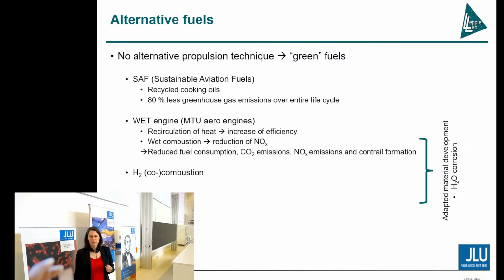Then there's also the so-called wet engine by MTU Aero Engine, where they recirculate the excessive heat and thereby increase the efficiency. And they introduce the condensed water from the end of the turbine in the combustion chamber and thereby have a wet combustion. And by this wet combustion, the NOx gases can be reduced. So in total, with introducing the wet engines, the fuel consumption can be reduced, thereby the CO2 emission, the NOx emissions, and also the contrail formation.